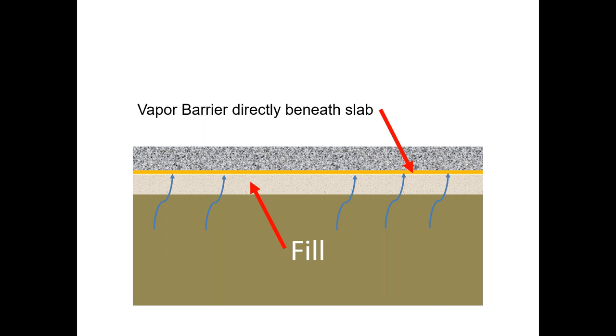If I tried to put some type of epoxy coating or something like that down there, I would have had issues as well. I would have needed to put down a moisture vapor transmission type coating, which Euclid pays me, but they don't pay me well enough to afford it. So I didn't do that. What I ended up doing was putting down ceramic tile, because it's a cementitious system and the adhesive is really not affected by moisture.